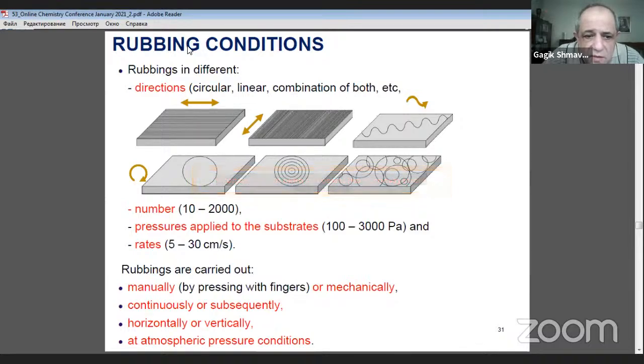So the rubbing process is very simple, an extremely short-lasting process. It takes about 150 seconds, and here you can see the rubbing conditions. We use different substrates, different powders, and rubbings are carried out in different directions, numbers, pressures applied to the substrate, and rates. Rubbings are carried out manually, continuously, or subsequently, horizontally or vertically, at atmospheric pressure conditions.